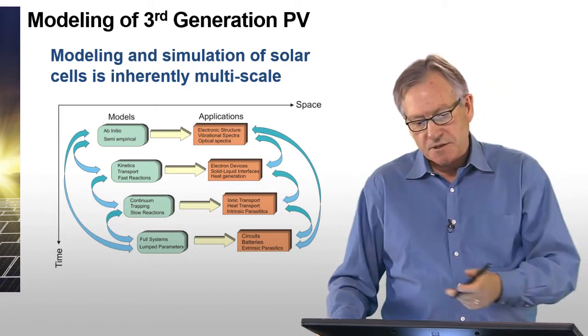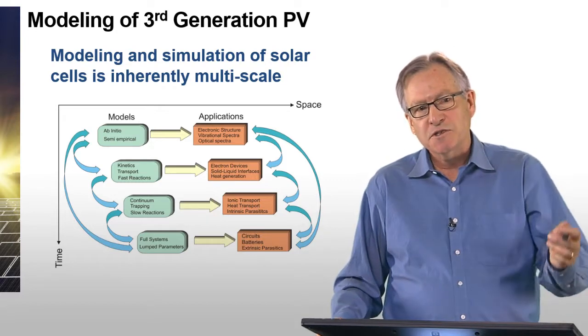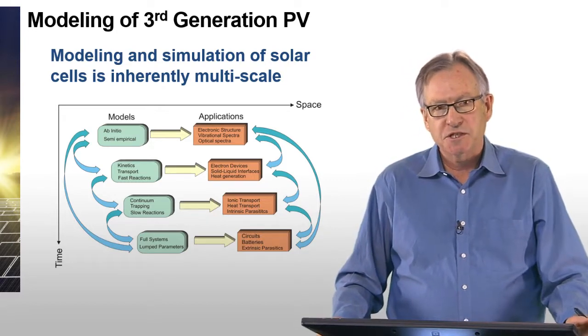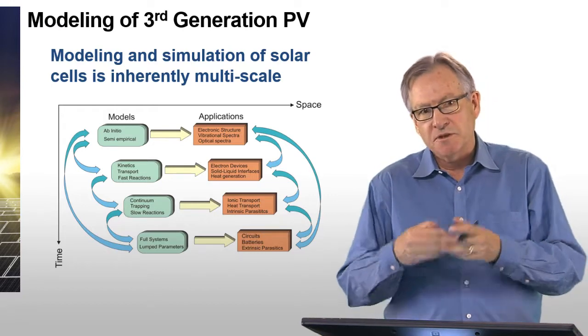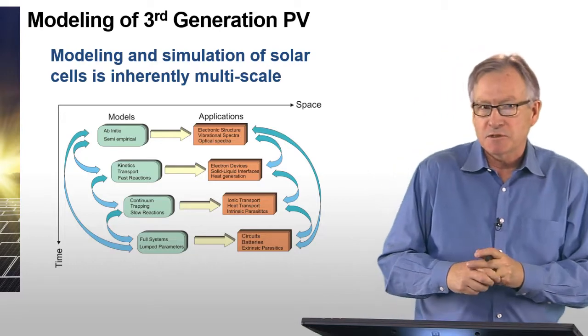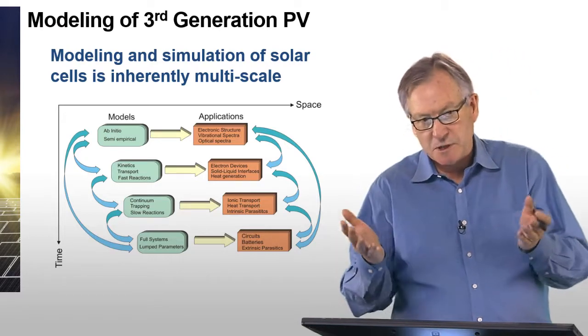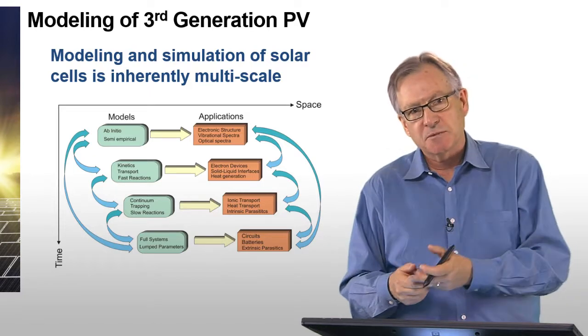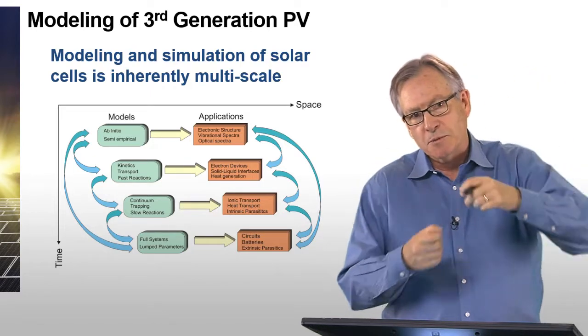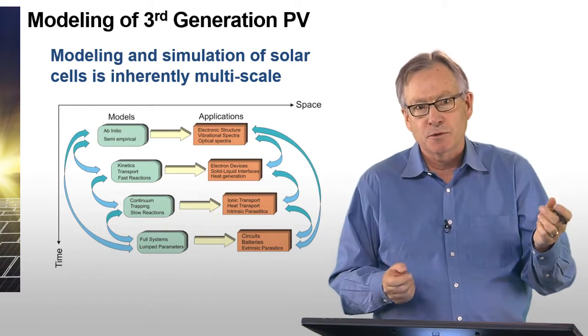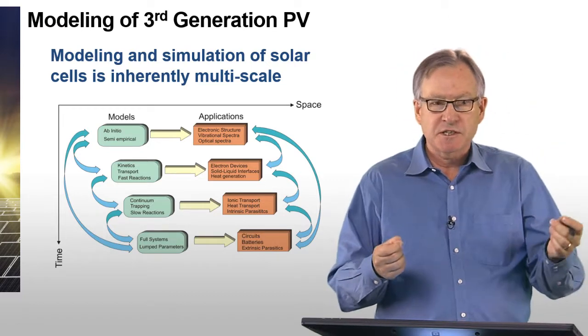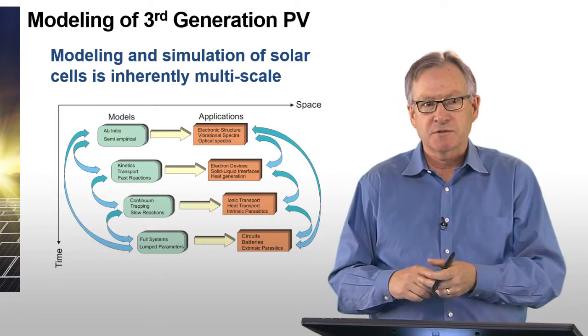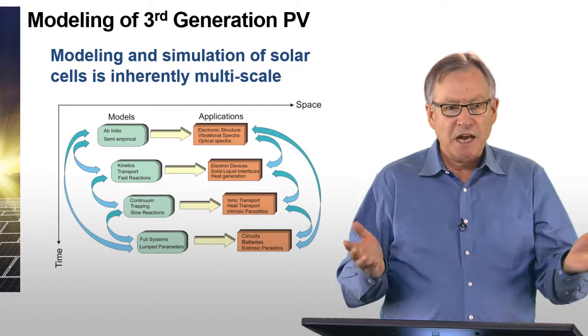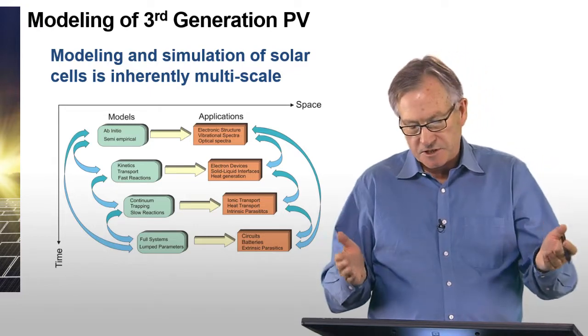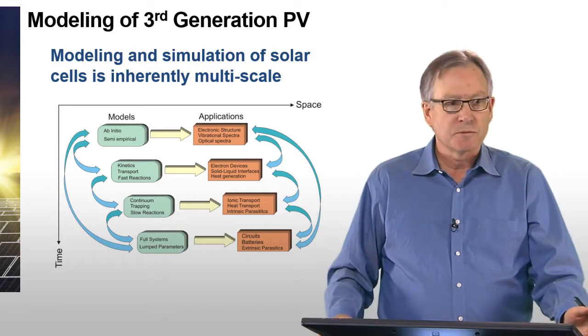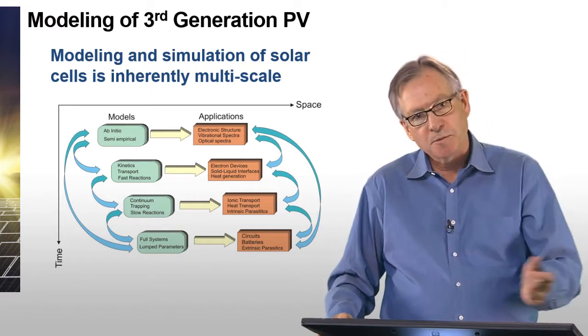We have basically, at very short time scales, the processes that are responsible for energy relaxation. That is, the emission of quanta of heat called phonons by the electrons. This occurs at a picosecond time scale, or 10 to the minus 12 seconds. On the other hand, recombination processes, that is, the electron and the hole actually recombining before being collected, occur on time scales that range from 10 to the minus 9th seconds to milliseconds, 10 to the minus 3rd seconds. So basically, you have over 10 orders of magnitude difference of time scales of the different events that are occurring. Okay, so this is one problem in terms of simulation, dealing with large temporal scales.